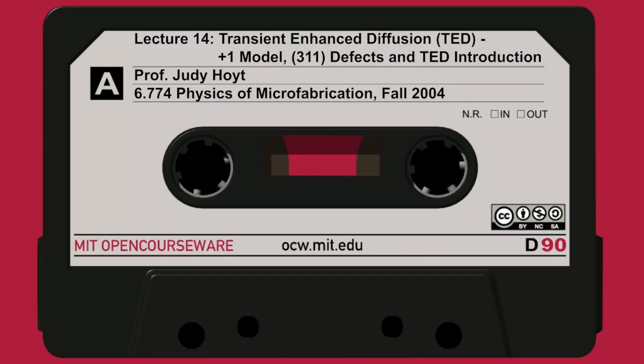Okay, given that little bit of experimental introduction, now we finally get to talk about how people model TED. I showed this slide last time. I just want to review what a 311 defect looks like. Here's a high-resolution electron micrograph, so this is electron microscopy at a very high magnification. In fact, you can see these little rows of dots. Each dot corresponds to a dimer, two silicon atoms. And the reason they're in such nice regular planes is because it's a single crystal material.